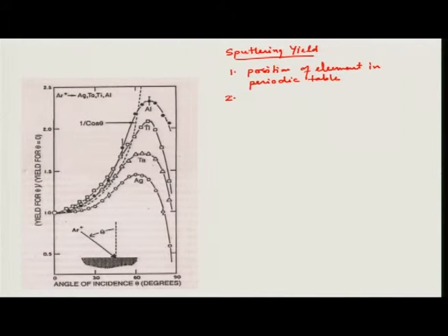Number 2, it depends on the crystal structure, and even in the same material, the close packed directions have high sputtering yield.